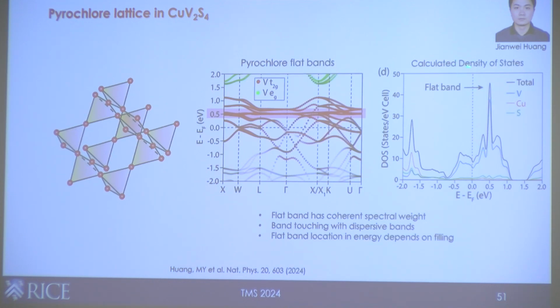In the DFT density of states, all the stuff near the Fermi level you can see is all vanadium. The copper are farther away. And you can see that here is this pyrochlore flat band, which is associated with the T2G vanadium sublattice. We started to look at this, but notice that the position of these flat bands is half an eV above the Fermi level.